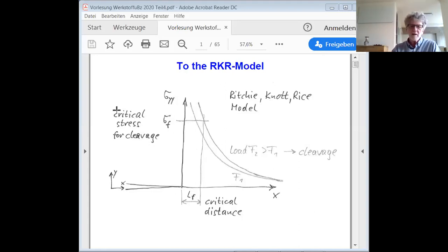The Ritchie-Knott-Rice model says that cleavage fracture can occur when a certain critical stress for cleavage, the so-called cleavage stress, here sigma F, is exceeded over a certain critical length. This critical length is denoted as LF. So you see here I could load F1. In fact, the criterion is not yet fulfilled because the critical fracture stress sigma F is only exceeded in some region smaller than LF. So you have to increase the load now. The criterion is now fulfilled.